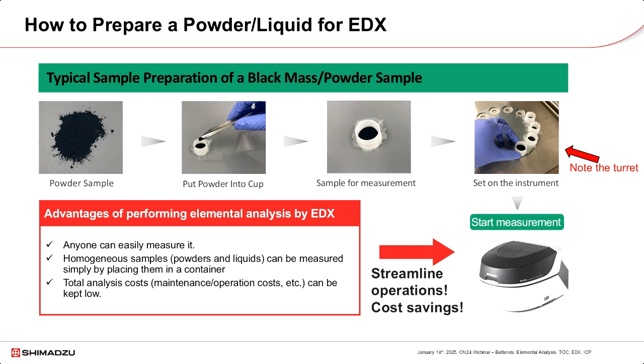The following is a typical sample preparation process for a black mass, a powder sample, or even a liquid sample. You would take your powder, and for example, you would take a spatula and put that powder into what is known as an XRF cup. The powder sits inside the cup and is supported by a transparent X-ray film that is made of a material like polypropylene or Mylar. You would take the cup, and provided that the EDX has a sample turret, you can load the turret up with up to 12 samples and then hit the start button.